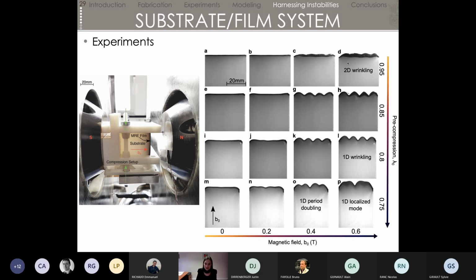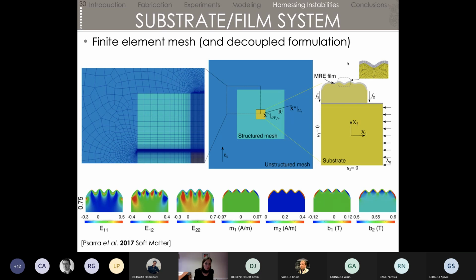So what we did again here was to model via finite elements. So again, when you're doing that, it's a huge mess in terms of mesh. You can see here on the right, you have your substrate in yellow. The film is just that little tiny blue layer or purple layer at the top. So there's very little MRE in your mesh. Around it, you have already a structured mesh from the air, and then because you need even more, a larger domain with the air, they ended up doing unstructured mesh. So you have a really large mesh for just a small sample.